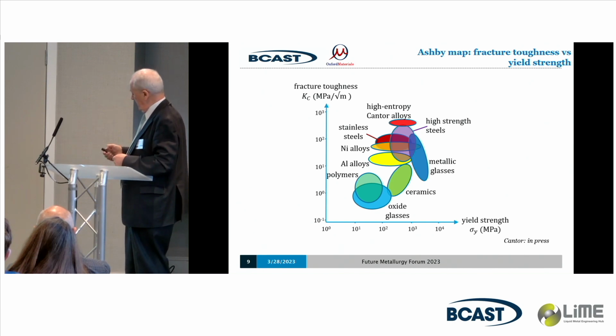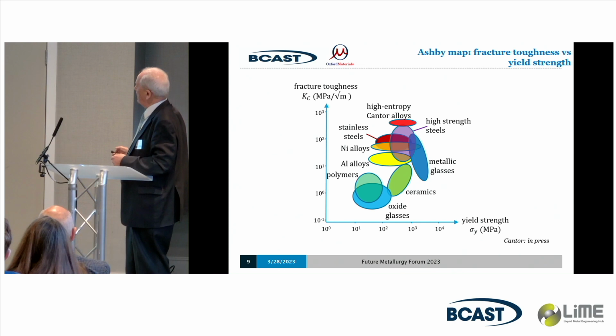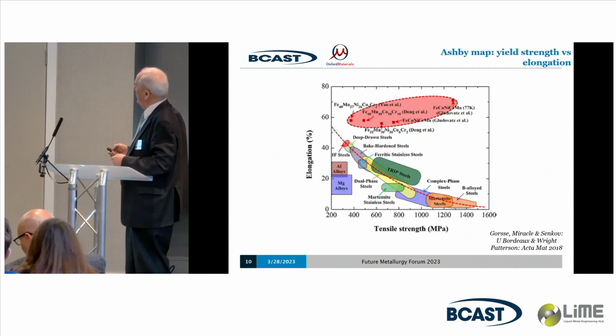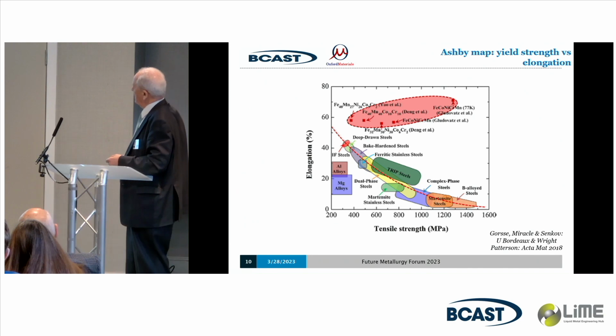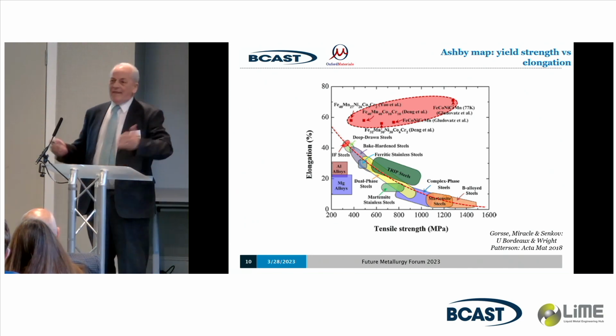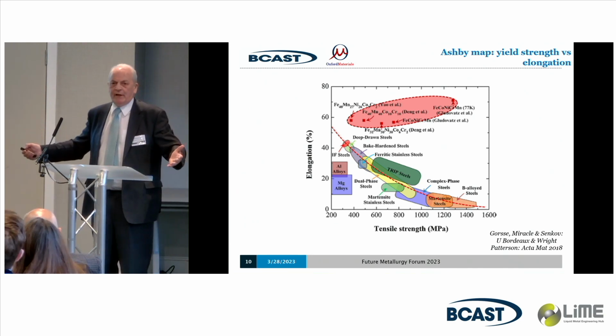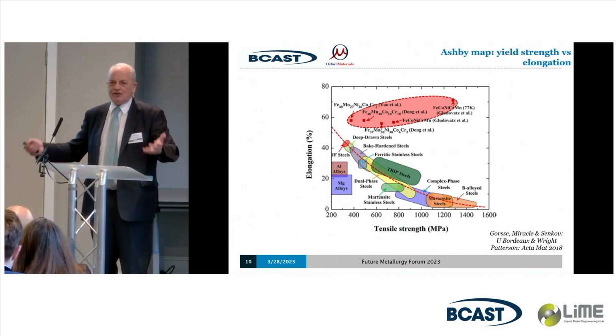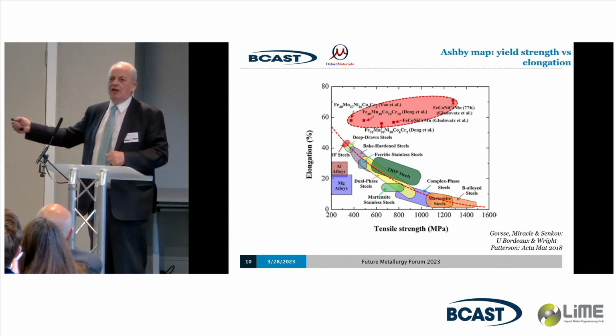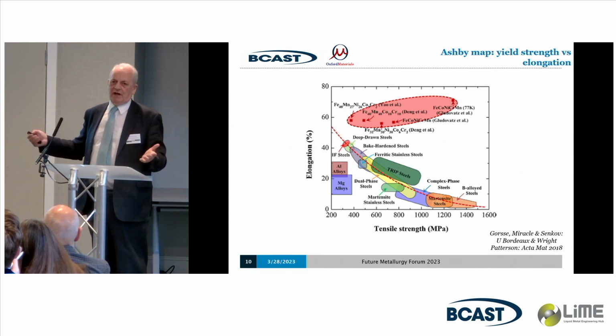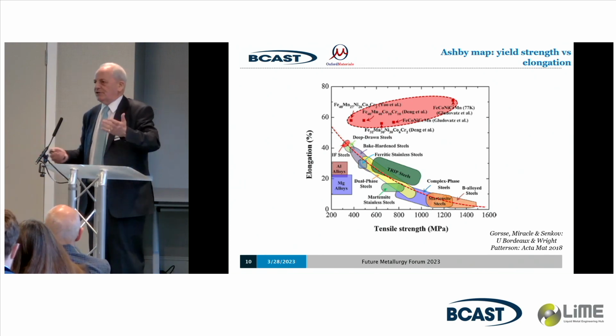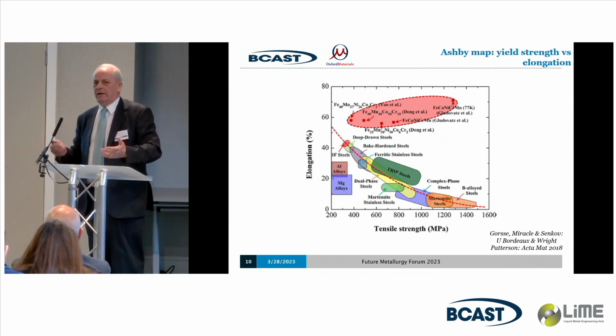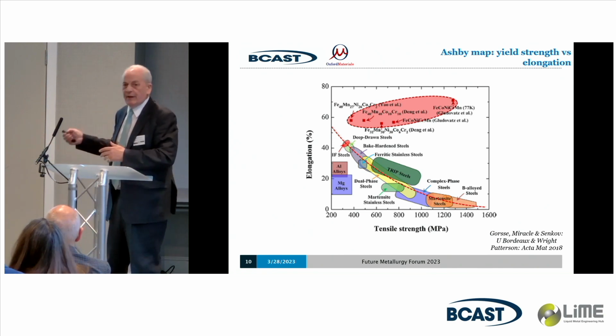So you can see where the Cantor alloys are, the FCC Cantor alloys. And if you home in, that's a comparison with lots of different materials. That's comparing it specifically to steels. These are some of the best steels, and there's the Cantor alloys. So people are excited about that. That's without any microstructural manipulation whatsoever, just a single phase FCC annealed structure. That's before you start doing clever things like precipitation hardening or grain boundary hardening or you name it. So there's loads of things you can do, and people are doing that.